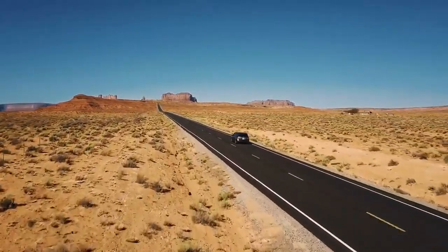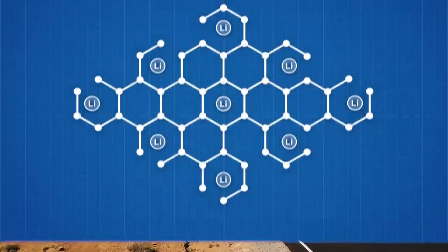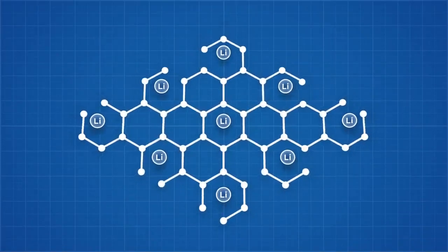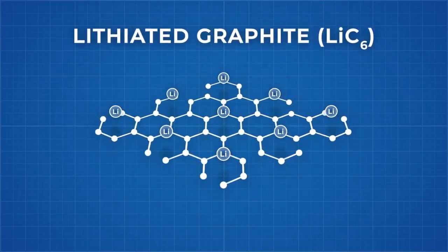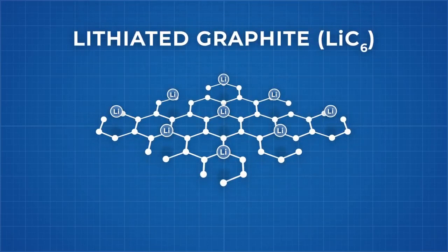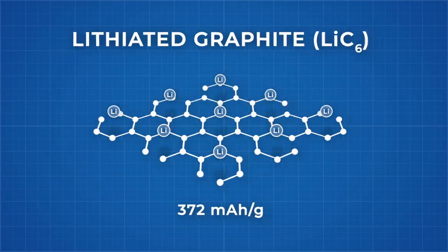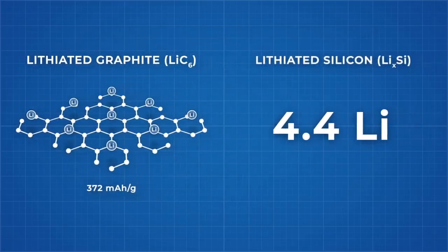For example, the graphite anode requires 6 carbon atoms to store a single lithium ion to form this molecule. This gives a theoretical maximum battery capacity of 372 mAh per gram. Silicon, however, can do better. A single silicon atom can bind 4.4 lithium ions, giving it a theoretical maximum battery capacity of 4,200 mAh per gram.